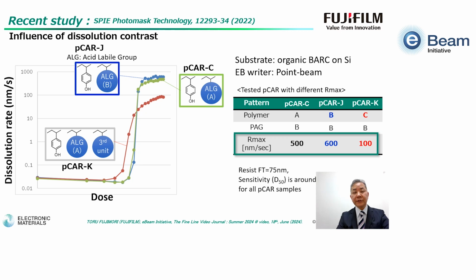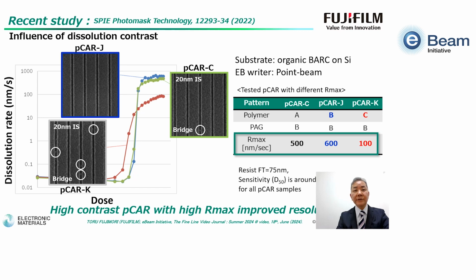The final topic is a recent study of EB resist for masks, from Photomask Japan 2022 from Fujifilm. A study of dissolution contrast using polymer structure, successfully synthesizing 3 different contrasts by using 3 kinds of polymers. Figure K looks low contrast, C looks high contrast, and J looks higher contrast. As a result of the lithographic performance, the higher contrast formulation, figure J, looks excellent, with no bridging and excellent LWR. Now keep going to improve for the next generation node. Resist materials development never stops.